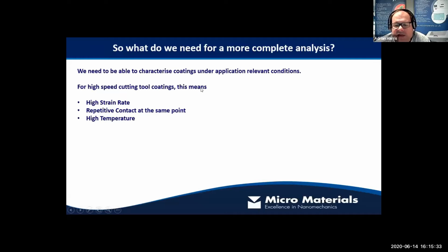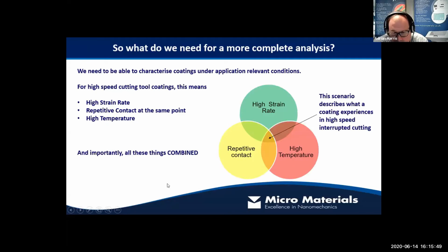Well, we need to be able to characterize coatings under application relevant conditions. So for high-speed cutting tool coatings, this means, as we said, high strain rate, repetitive contact at the same point, and high temperature. Even more importantly is combining these things together, because in a high-speed interrupted cutting operation, we've got a repetitive high strain rate contact with frictional heating.